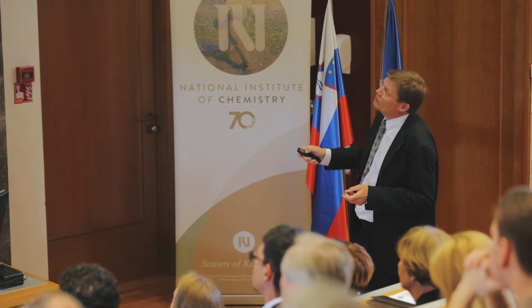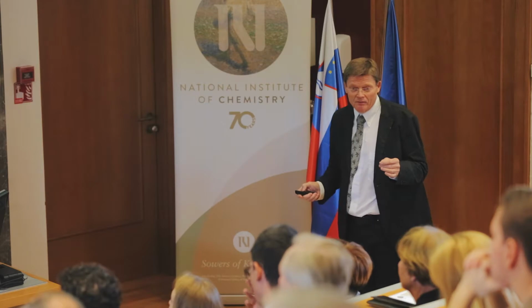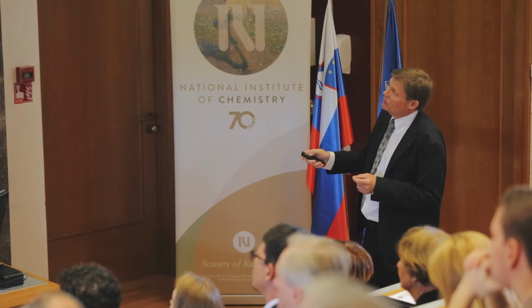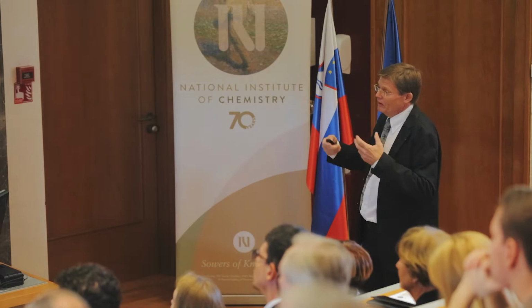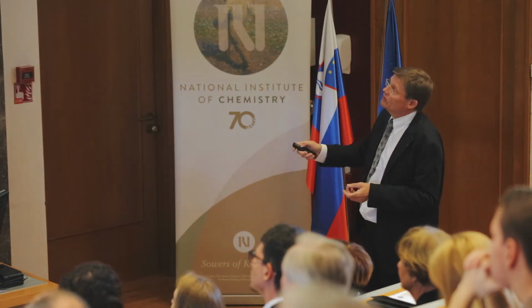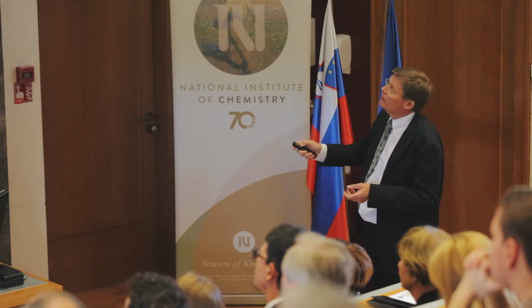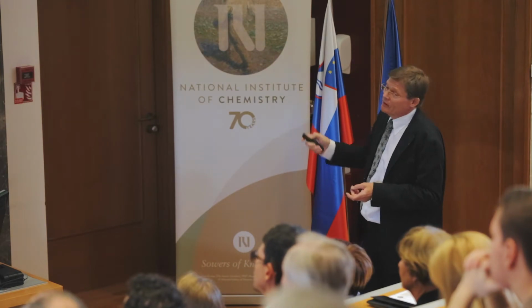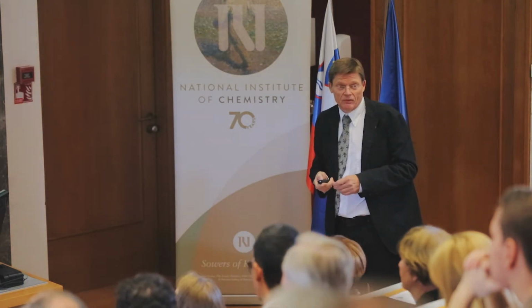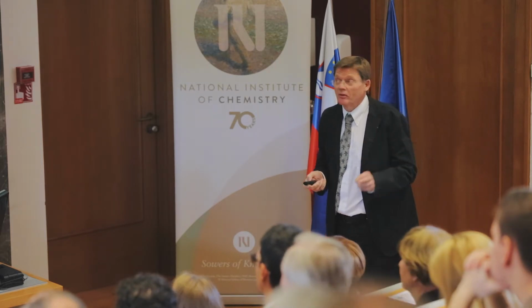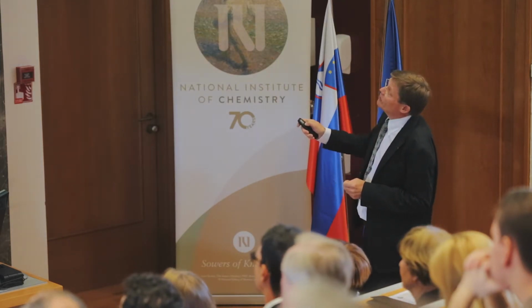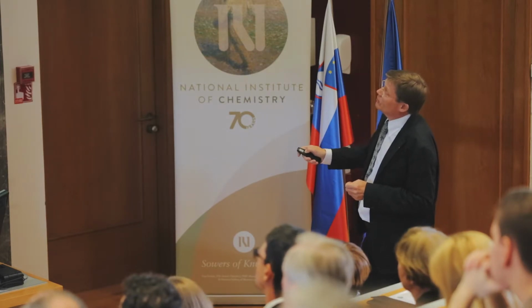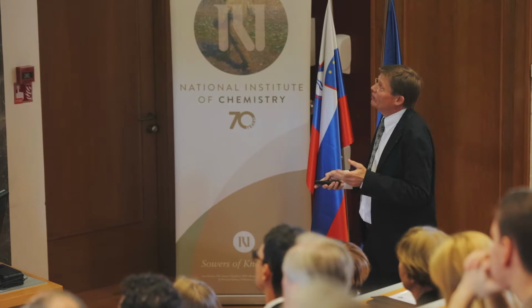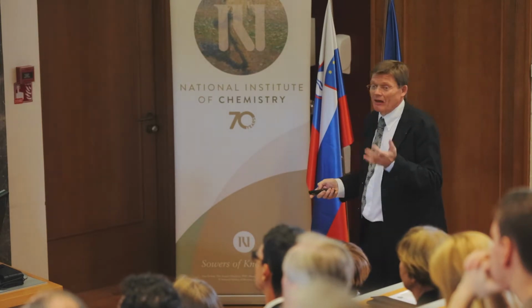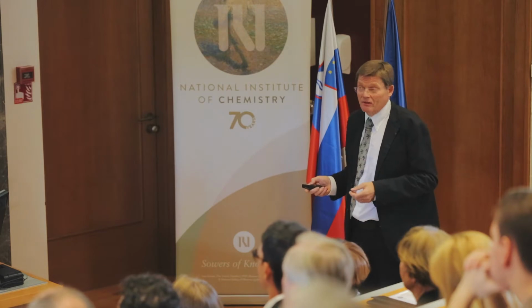And then we did the following. We took this material, this methyl ammonium lead iodide. We plugged it in between two graphite electrodes. We switched on a current. Then you saw this polarization curve, which tells you, when you compare this to this, that the material is primarily an ionic conductor, also an electron conductor. And then if you evaluate this kind of transient, you can do this also very nicely. Anyway, the anomalies are just normalities when you consider this as a mixed conductor.